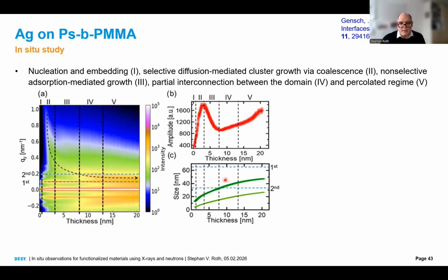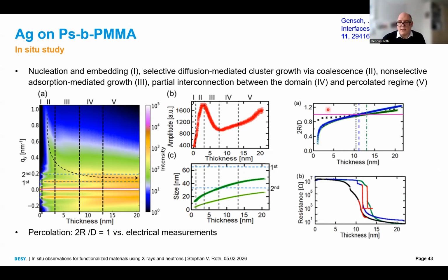We can then deduce all the sizes. We can again look into 2R over D, and this is now very important. You see here these different vertical lines. This is what we deduce from our structural model as the projected percolation threshold, and we measure this also.